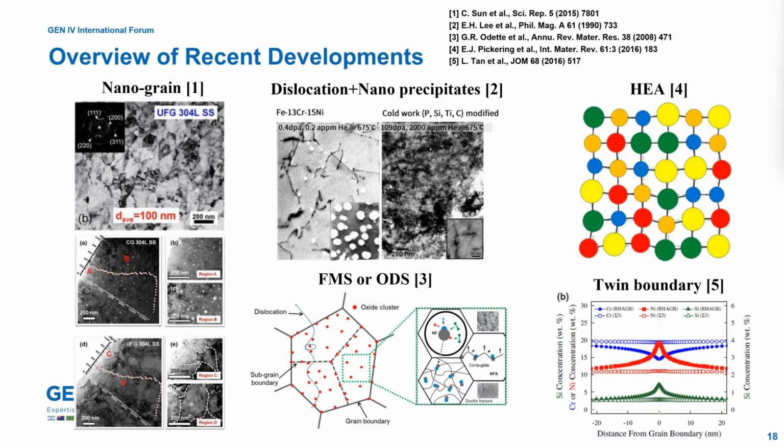And in addition, as mentioned on the previous page, three general strategies can be employed to increase radiation tolerance in materials: radiation resistant matrix phase, immobilized point defects, and engineered high sink strength microstructures. Overall, the strategies are based on the introduction of various microstructural features which may act as a sink site for point defects. For example, as you can see, nano grain, which has 100 nanometer scale grain,